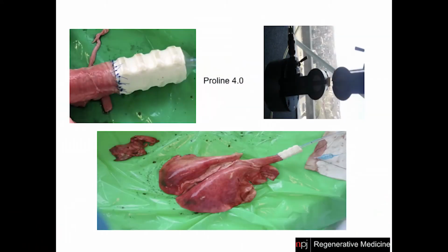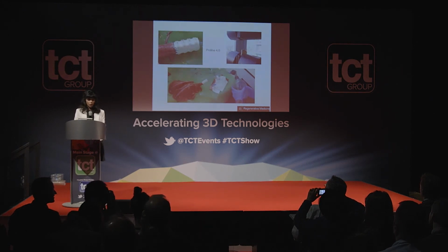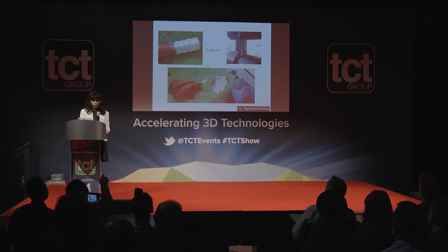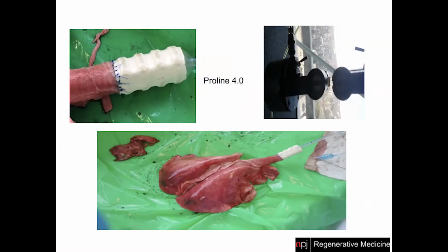And then we wanted to see if it's okay when attached to the rest of the respiratory tract. We obtained a porcine lung system, and this is a video I wanted to play, to see that it actually facilitates the airflow and expands and constricts the lungs accordingly, which it did. We also tested its compatibility when attached to a suture, and it was okay. So we were successful in clarifying this.